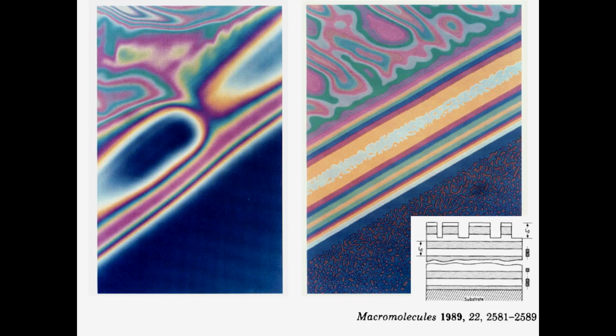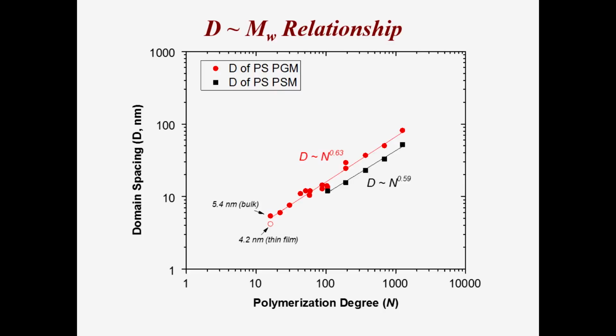And that tells us that the distance from the center of one domain to the center of another domain, the pitch, is 4 nanometers. That's the smallest anyone has seen with these types of materials. That corresponds to roughly about 30 DVDs on a quarter, all right, if we can really get the resolution and the lateral ordering that we think we can. And if you look at the domain spacing as a function of the degree of polymerization, this happens to be the polystyrene polyglycerol methacrylate as a function of molecular weight. This is where we're at right now, and we're at a pitch of around 4 nanometers. And that's great. That's marvelous.